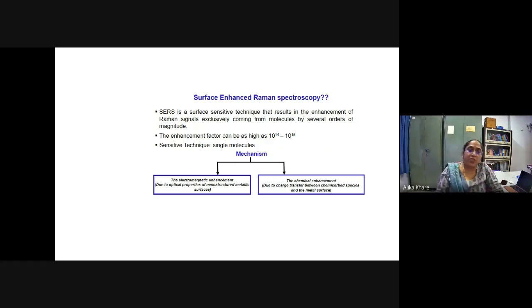Raman spectroscopy depends on the induced dipole moment. If the induced dipole moment is large, the Raman signal will be large, otherwise it is very small, and we know that Raman signals are normally very small. In the presence of these nanoparticles, they have excessive electrons, so they create a sort of polarization, and once they create the polarization there is generation of an electric field, and because of that the polarizability of the molecule increases, hence the signal increases. This is one way.